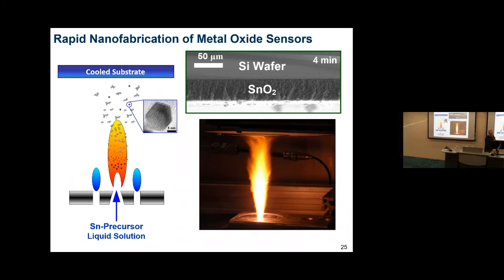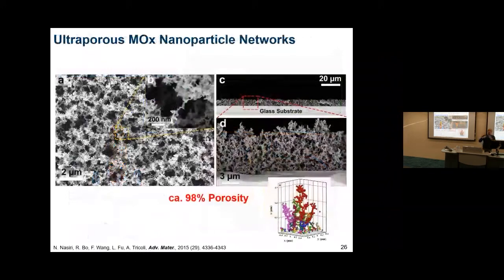This is 40 micrometers or something. And if you look at the structure, it's the same structure we simulated before, very open, 98% porosity, which is very good for gas sensing, for example. It's not good for other things—if you put it in a liquid, it disintegrates. So then you have to add on, but just to give you an example.